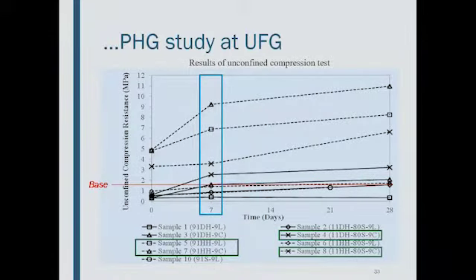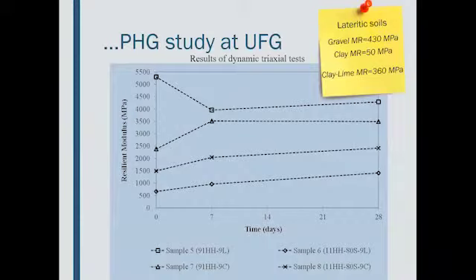And then this is a result for the unconfined compression test. You can see that these mixtures with HH present good results. And when I have the dihydrate type, maybe with the soil, you can get some good values for the strength too. And about the resilient modulus, we got good values for the mixtures with the hemihydrate type too. And these values are higher than those that you observe for traditional materials that you use for subbase and base of flexible pavements. So by mechanical tests, these results show that it's possible to use these mixtures.